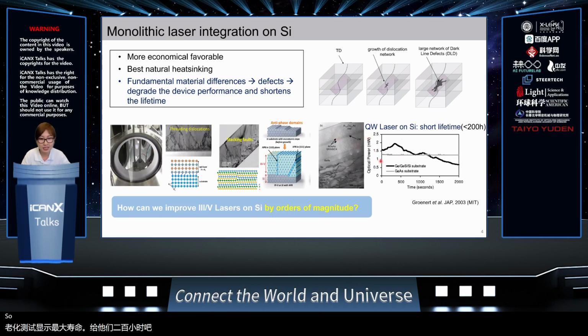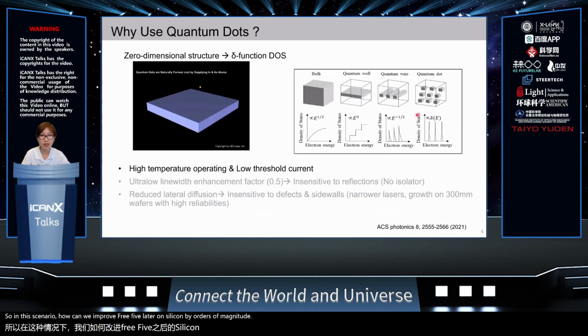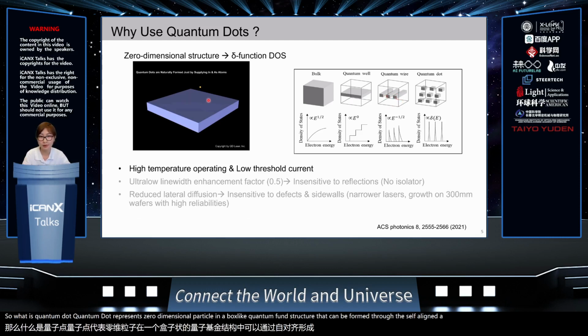So in this scenario, how can we improve the III-V laser on silicon by orders of magnitude? The strategy here is that we deal with the active region, and quantum dots can be used instead of quantum wells. So what is a quantum dot? A quantum dot represents a zero-dimensional particle-in-a-box-like quantum confined structure that can be formed through a self-assembled process using indium arsenide and gallium arsenide layers.